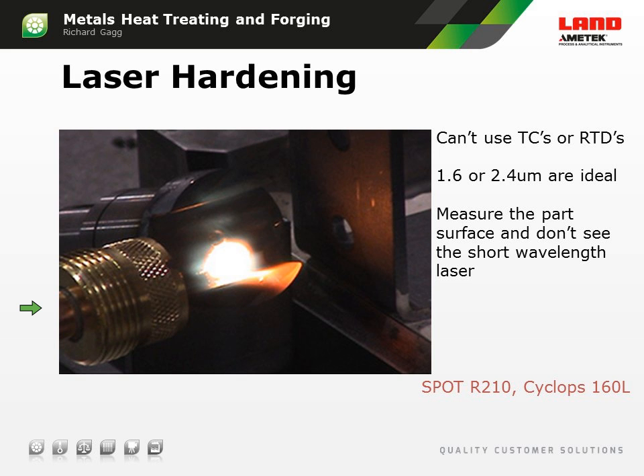And so if you use a thermometer with a 1.6 or a 2.4 micrometer response, it does not see the laser reflections at all. It only measures the surface of the part. So by using something like a Spot R160 or a Spot R210 or a Cyclops 160, you're working at a wavelength that does not see that YAG laser and is not affected by it. So this is a perfect application for using one of our Spot ratio devices or a Cyclops 160. Again, you can't use thermocouples or RTDs because the laser would heat up that sensor and it would give a wrong reading. So you have to do it by non-contact methods.